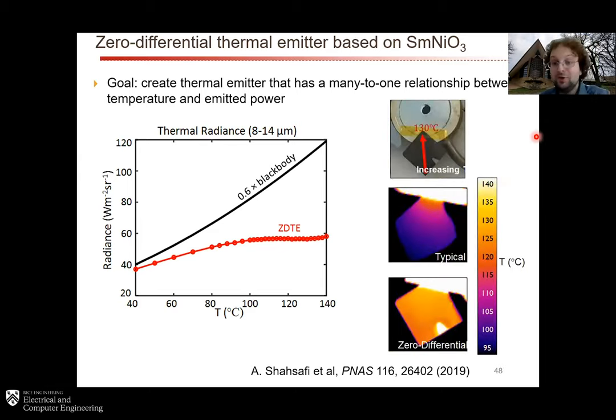And you can see that in this experiment over here, where we took a little circular heat stage and we took the sample and we taped it with Kapton tape on the edge. We heated the heater to 130 degrees. And because the sample is essentially kind of hanging off in air, it's hotter here, but it's colder here. And so here's an infrared image of a typical object, which is not zero differential. In this case, it's just a piece of sapphire. And you can see that it's hotter here and cooler here, and it has a gradient in between.